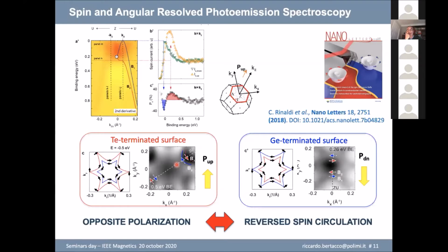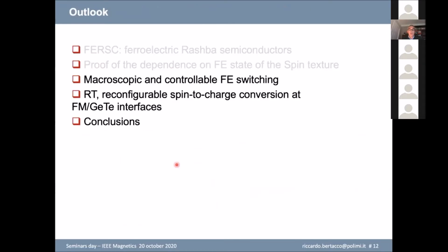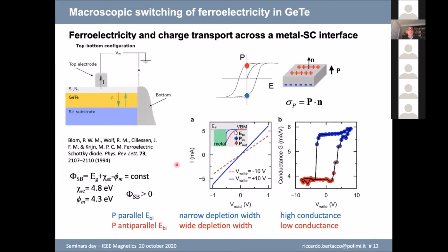So to be able to control the ferroelectric states, we developed a way for controllable macroscopic ferroelectric switching. And the idea is this, something related to the theory of ferroelectric diodes, dating to 1994 or so. You see this paper here by Blom and co-workers. So just looking at the IV characteristic of the gate. You see here the structure. We have a metallic gate on top of a germanium telluride film, with an interlayer or without it. It doesn't make a big difference.